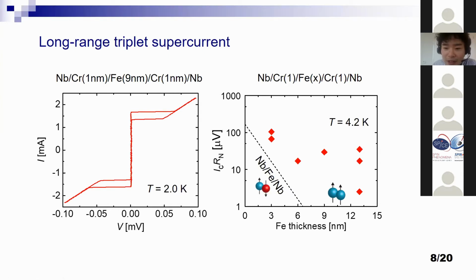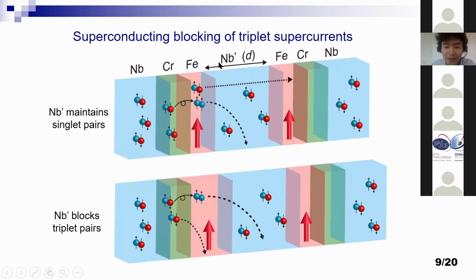But if we insert a chromium pair converter, then we can observe large supercurrent even for 13 nanometers thick iron samples. So recently, we are more focusing on the physics of this long-range Josephson current itself rather than just its creation. And I would like to show today the results of this structure.